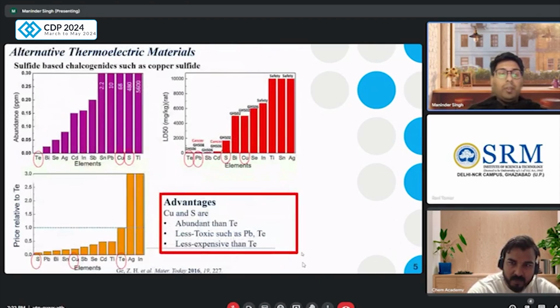So we need to look for alternative thermoelectric materials. The first condition has to be abundance. As you can see, tellurium has low abundance. So that's why we chose copper and sulfur, which have high abundance, and the toxicity levels of copper and sulfur are lower than those of tellurium and lead.